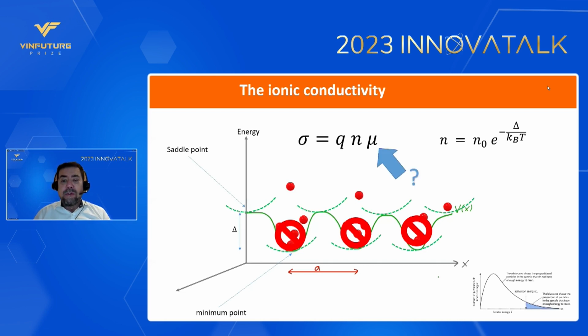Now, the difficult question is that the conductivity is not only the number of ions. The conductivity is given by the charge of the ion, the number of ions, and the mobility of the ions. So although you see straight lines in the experimental data, the real question is, what determines the slope, which is essentially given by the ion mobility? So this is the big question to be answered in this field. What determines the ionic mobility? What are the microscopic parameters that control the ionic mobility of an ionic crystal?